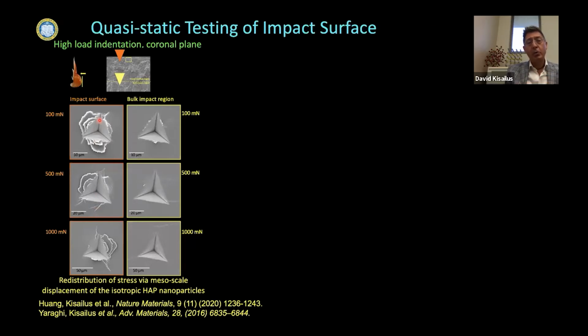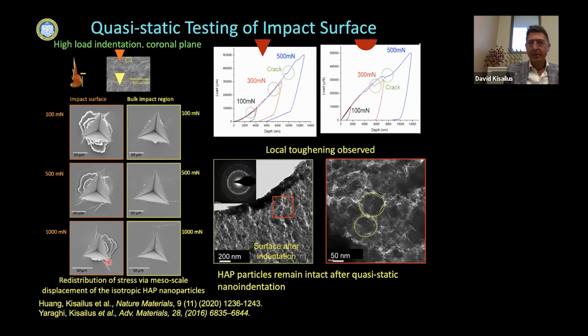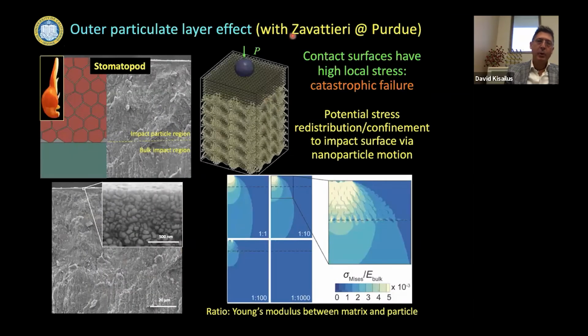And we also polished away the particles and subsequently performed the nano-indentation. So where the particles were, you see this pileup occurring, so this toughening this way. But when we remove the particles, we see cracks that are generated at these corners. So we believe this toughening is due to what we call mesoscale displacement of these particles. And this just shows some of these inflections here during these nano events toughening.